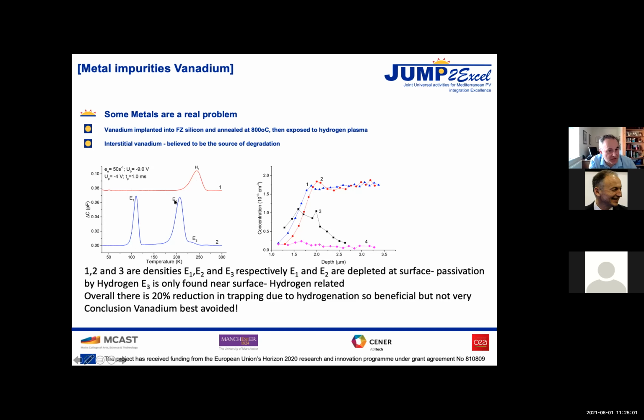We deduce that because they've appeared when we put vanadium in. If we put other metals in, we don't see them. They also have some dependence on depth. We can measure depth with DLTS for a few microns anyway. We can look at the concentration of this particular trap away from the surface.